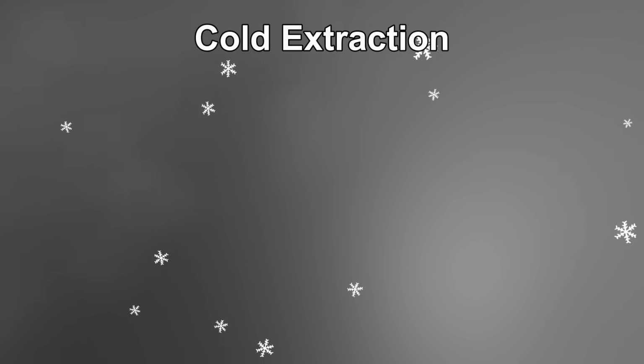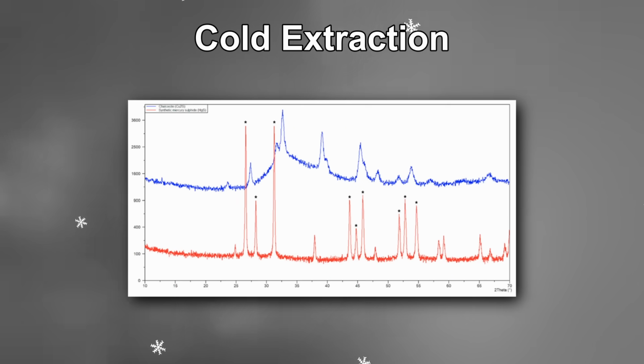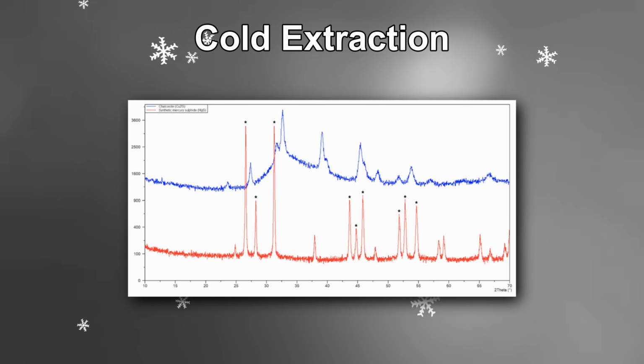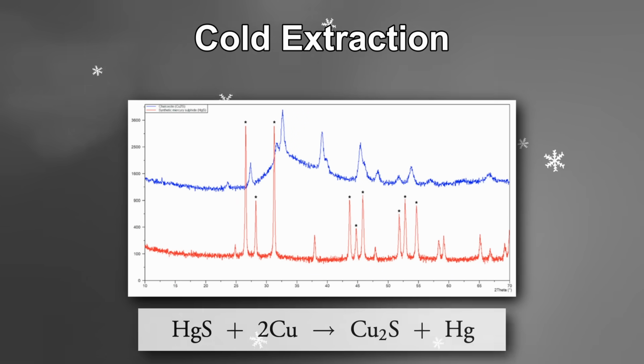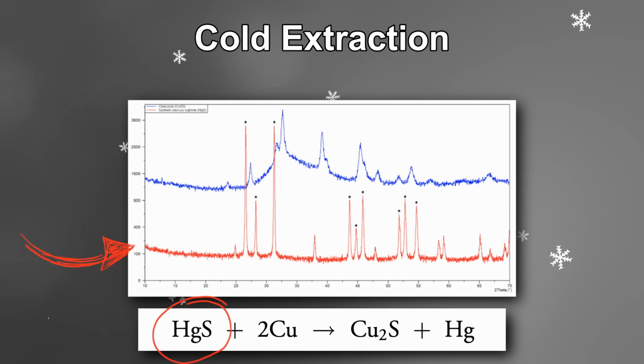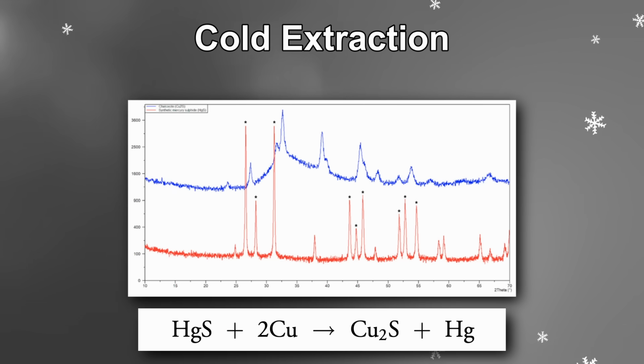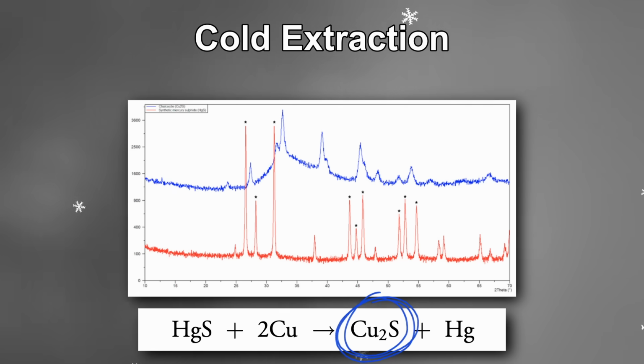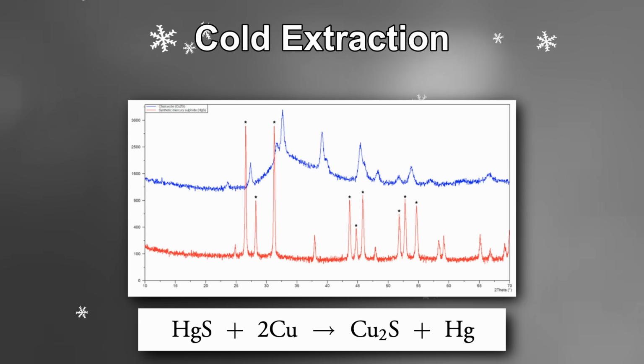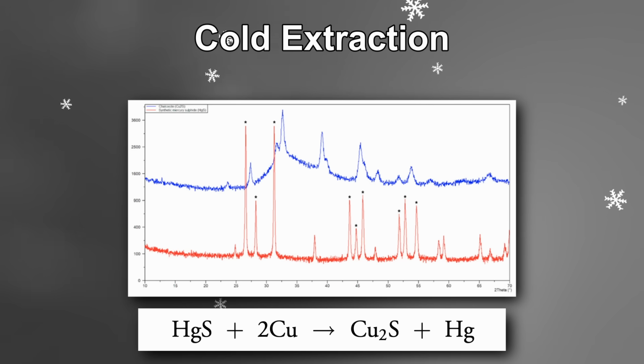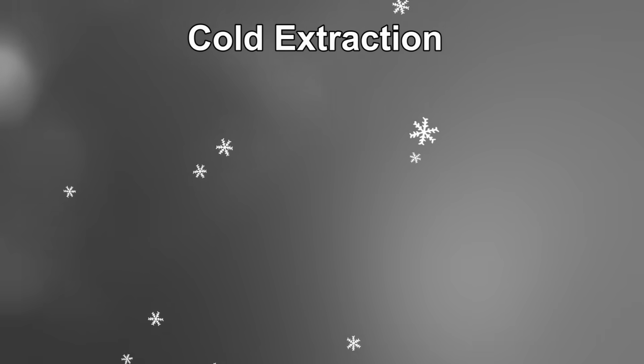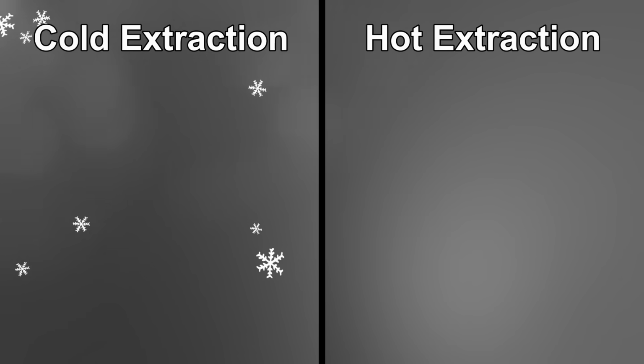They then used a technique called X-ray diffraction to analyze the crystal structure of their product, and they found that the original mercury sulfide, shown in red, had been transformed into a completely different crystal structure, that of copper sulfide, shown in blue, giving evidence for the success of the reaction. So, just the simple act of grinding cinnabar with copper and vinegar can produce liquid mercury. How about the hot extraction techniques?